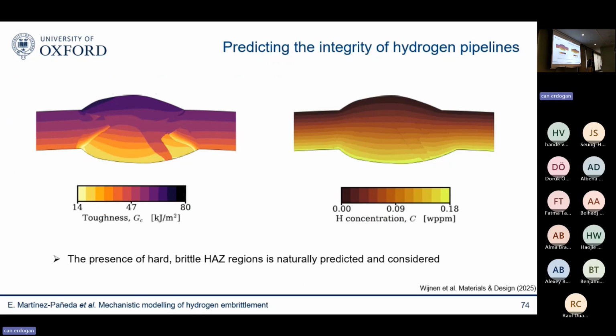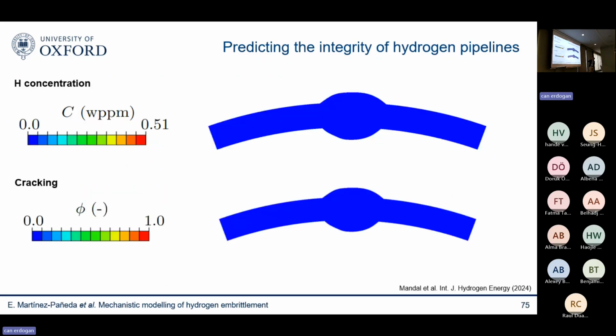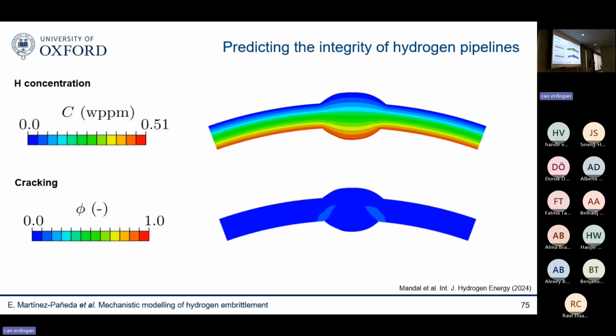But we are able to incorporate that microstructural heterogeneity in the model, and then basically we expose the pipeline to a hydrogen concentration, and we see where things fail. This is what you see here. So this is the weld and the pipe. At the bottom, you see the phase field. At the top, you see the hydrogen concentration. We're increasing progressively our pressure, 100% pure hydrogen, and we're seeing when a crack will develop. And then eventually, as you see, pop, a crack pops out, and your pipeline has failed. So this is good because then we can test a wide range of conditions.